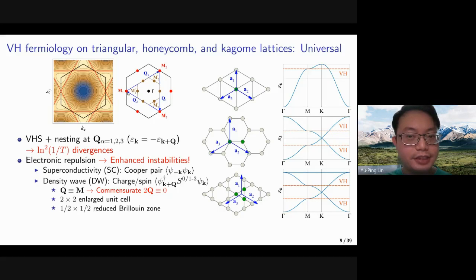Because the momenta are equivalent to the saddle point momenta, they will be half of the reciprocal lattice vector. It means that the momentum q's are commensurate to the lattice. And because our wave vectors are halved, our periodicity in the lattice will be doubled. For example, our original periodicity is one lattice vector, and now it will be two lattice vectors. It means that our unit cell will be enlarged into a 2x2 structure. Meanwhile, in the momentum space, because our wave vector scale is halved, it will become a 1/2 times 1/2 reduced Brillouin zone, and we indicate it by the brown hexagonal region here.